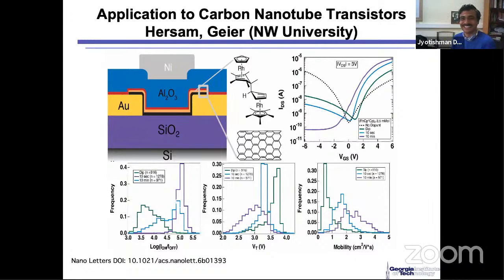No. I cannot. This is a device architecture that Mark had spent quite some time optimizing. He didn't explain it to me. It was well known at the time. The only thing that I can tell you is that he had this optimized device architecture for what he was doing with N-channel transistors. And we said, what if you expose the carbon nanotubes to a dilute solution for 10 seconds, just 10 seconds, before you deposit the alumina and the nickel. That's what I can tell you. The rest of it, I just don't know.